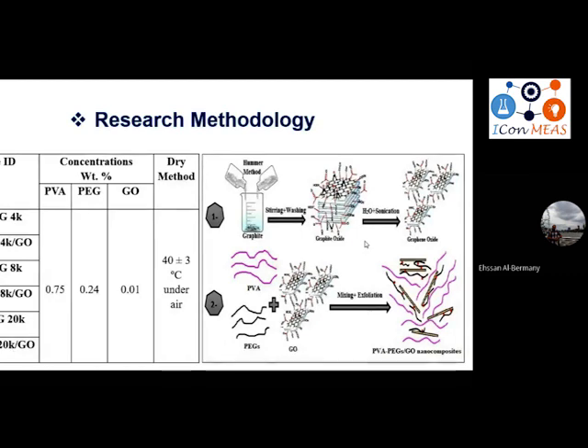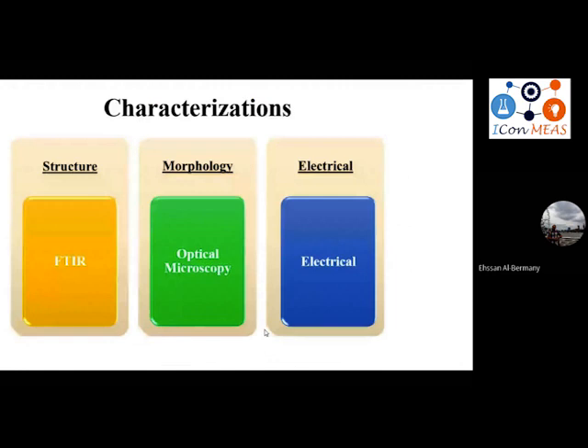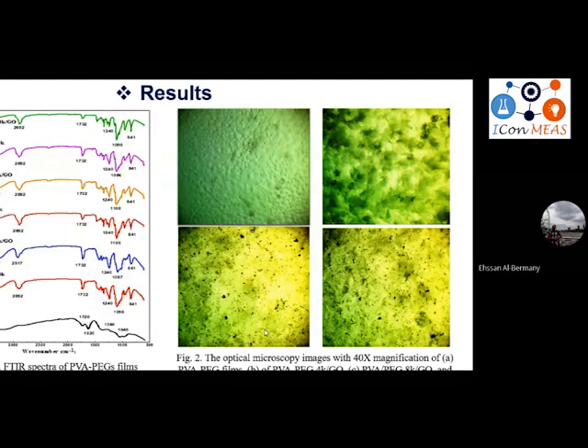The second graph, on the right side, sorry, has two steps. As we mentioned before, the graphene oxide was prepared at the University of Sheffield by me, and we used the Hummers method, the famous method to prepare graphene oxide from graphite by a chemical method, and then we used these steps to prepare the nanocomposites. For characterization, we used FTIR for the structure and optical properties, optical microscopy for taking images of the material, and for the electrical properties we focus on AC specifically.